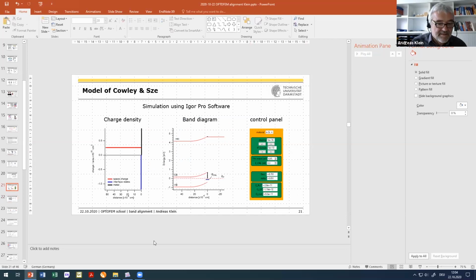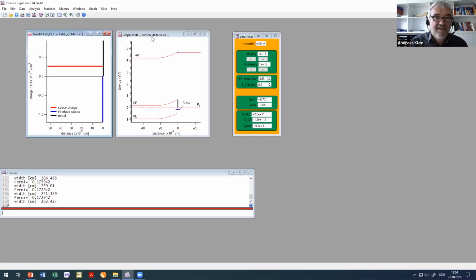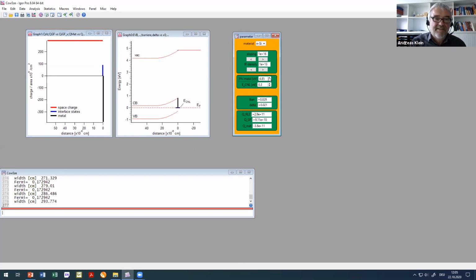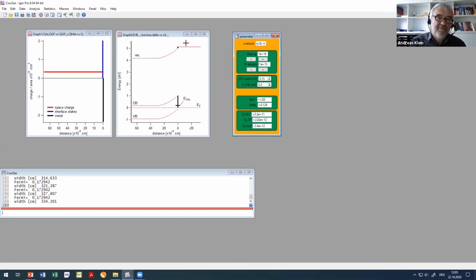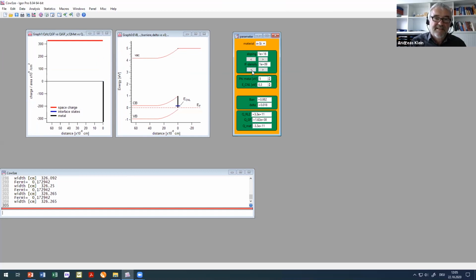So that's a simulation. It's in principle the same figure as in the slide. Okay, if now I change the work function of my metal, you see that the band bending is changing. Now the position of the charge neutrality level at the interface is also changing. But what you already see is that the vacuum level is not perfectly aligned. And that's because the charge in the interface states is quite significant. If we go down with the density of interface states, so 10 to the 9 per square centimeter, that's not a lot.